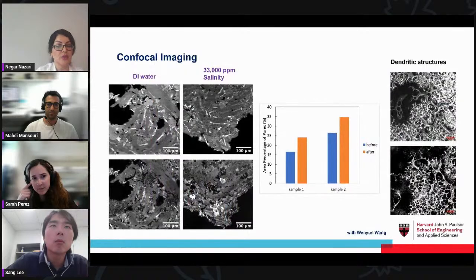So then we wanted to see if we can actually quantify any of those changes that happen on the surface of the basalt. So we put the surfaces under confocal microscopy and confocal imaging. The interesting thing is that we did not expect the confocal imaging to be useful because it's a rock surface. We don't have a transparent surface, and we were not that optimistic.